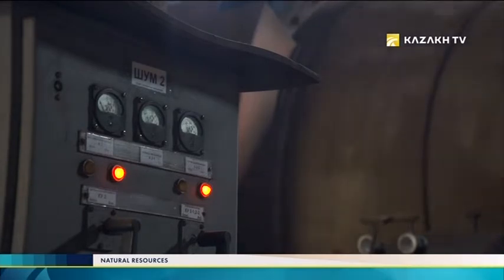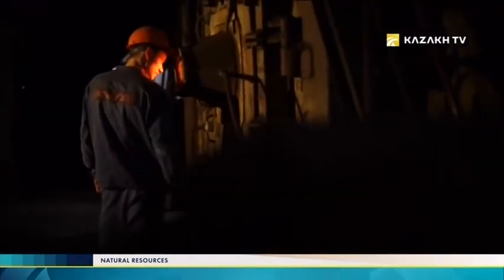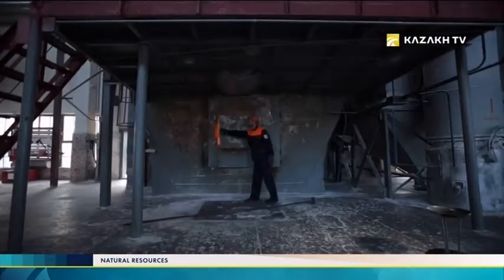Red mud, containing 22–23% of aluminum, is delivered to the sintering unit. In the sintering unit, more valuable components are extracted, and only 4–4.3% of aluminum remains in wasted sludge. Such way of double-stage alumina extraction is called Bayer parallel serial method of sintering, which is applied only at the Pavlodar aluminum plant.